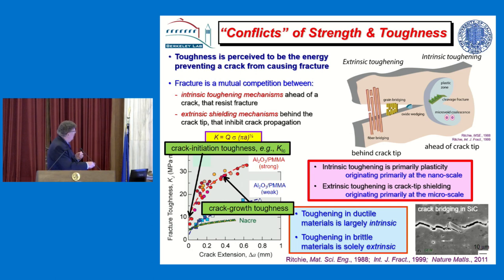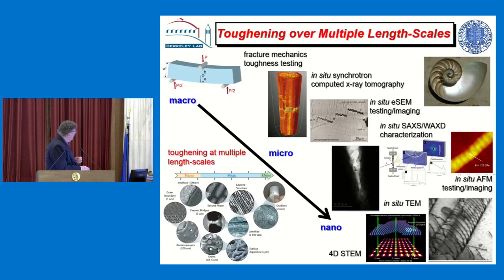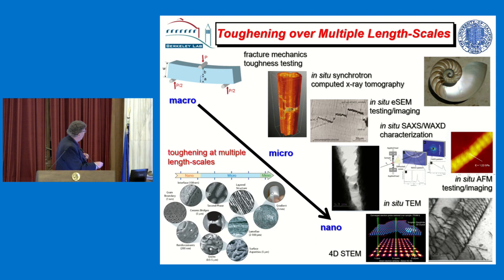Now, as I said, ductile materials are generally toughened intrinsically, brittle materials generally toughened extrinsically, but biological materials seem to develop both of these mechanisms in a rather seamless fashion, which is a very clever way to generate resistance to fracture. And I'll show you some examples of that. To do this, we have to look at a lot of length scales because we're dealing with mechanisms at the nanoscale all the way up to quite coarse grain scales.